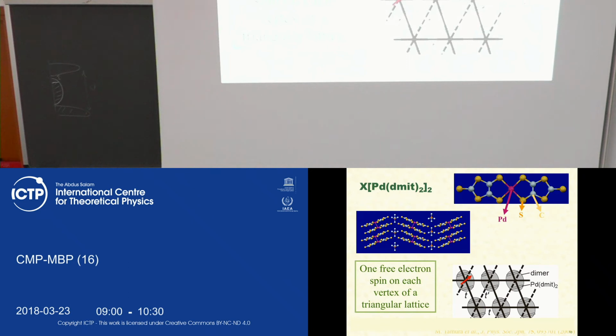I already mentioned Luttinger liquids as one example, which behave in a very different way than the Fermi liquid. In particular, the excitations in Fermi liquids are electrons and holes, well-defined excitations, which is proven to be true in 2 and 3 dimensions and high dimensions. However, it is also proven that in one-dimensional systems, fermionic excitations do not represent the good language of quasi-particles, because the quasi-particle lifetime is sufficiently short, and the inverse quasi-particle lifetime is comparable with the energy of quasi-particles. So quasi-particles are badly defined.